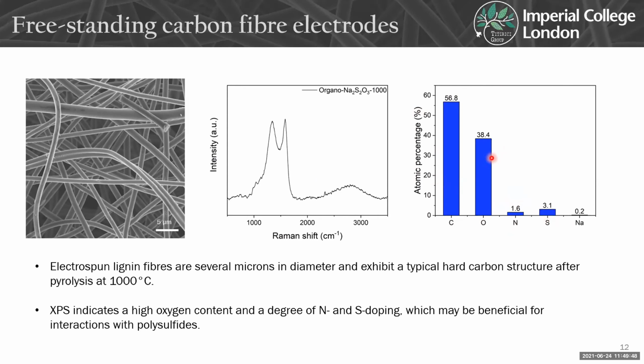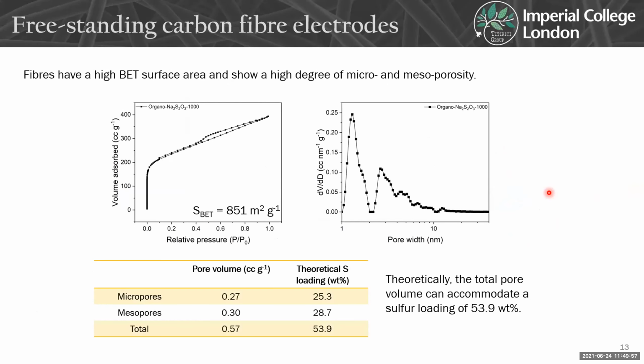And so we think that these might be quite beneficial for interactions with the polysulfides during battery operation. So then in terms of the porosity, it's got quite a high surface area of around 850 meters squared per gram. And then we've got a mix of micropores and mesopores. So looking at the pore volume then, we can see that if we calculate a theoretical sulfur loading, in terms of what we can put into the micropores and the mesopores, we can accommodate, if it's just in the pores, around 54 weight% of sulfur. So it's possible to accommodate quite a large amount of sulfur purely within the pores and not even on the surface of the fibers.